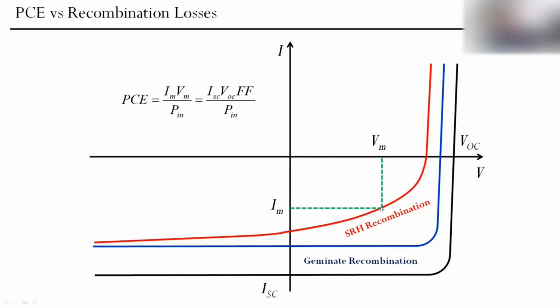So it's another feature of trap-assisted recombination. It also reduces fill factor. So we technically reduce all three parameters here in the numerator, and definitely our performance, like PCE, drops. So that's why we need to understand the physical nature of this geminate recombination and trap-assisted recombination, find a way to quantify it in order to apply it to different types of organic solar cells, and understand how we can reduce it, or what is the relationship between these undesirable recombination processes and chemicals, for instance, the chemical structure of the molecules which we use.